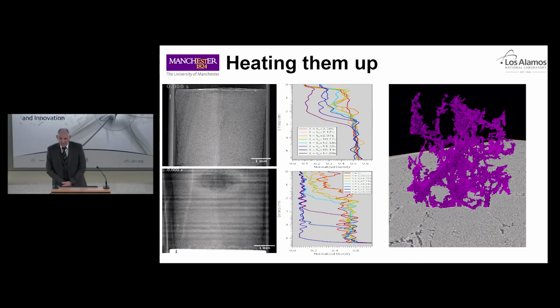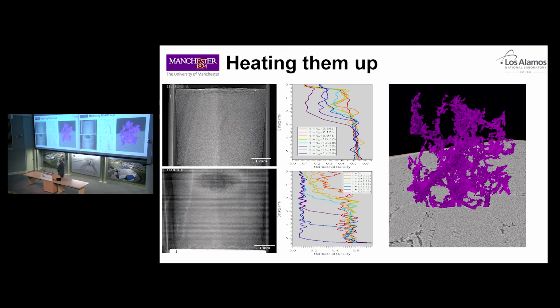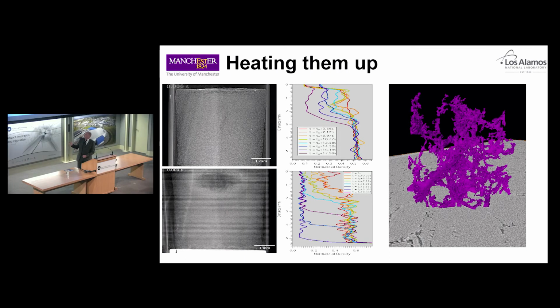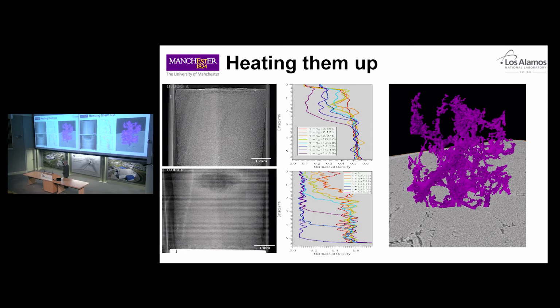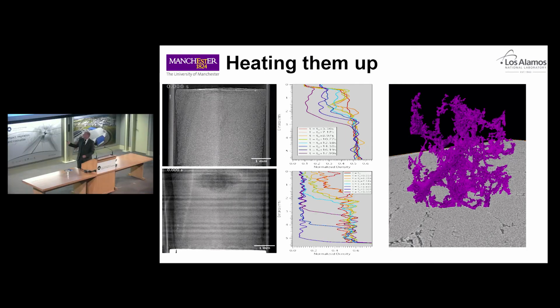So how do we find out why these materials are responding? It's because of the defects they contain. This is a simple way of seeing how these materials respond. These are explosives, heated up uniformly in a bath until reaction starts reasonably enough down the central axis. And at an individual point, we can see the creation of pores within that material as it reacts. So whilst this is a uniform heating, the sort of heating it gets during storage, it's producing gas in these volumes as it starts to react to the highest temperatures. And it's that that gives rise to these events that we can't predict.